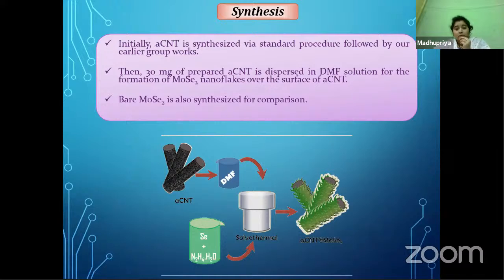First, amorphous carbon nanotube is synthesized via the standard procedure followed in our earlier works, using ferrocene and ammonium chloride. After that, we used 30 mg of the prepared amorphous CNT for the formation of MoSe2 nanoflakes over its surface under a low temperature hydrothermal process. The collected powder is again annealed in nitrogen atmosphere at 450 degrees centigrade. Pure MoSe2 powder is also synthesized for comparison using the same procedure.